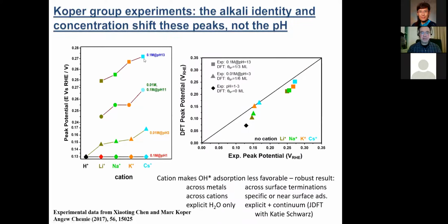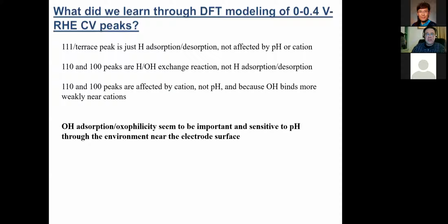And we have some nice papers, some nice DFT experiment agreement here. DFT peak potential, experimental peak potential, various cations. So we seem to know that what's going on here is that changing the electrolyte isn't really doing anything to hydrogen adsorption. There's no effect of changing this electrolyte property, in this case pH or cation concentration, on how hydrogen interacts with the electrode. All of the effect is what the electrolyte environment does to the interaction of hydroxyl groups with the surface. And that's some detailed surface science.